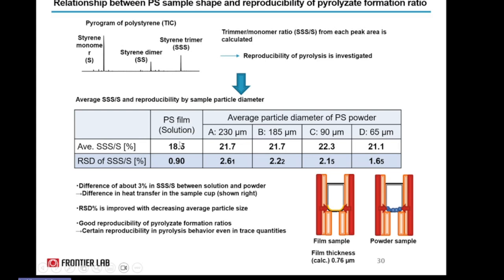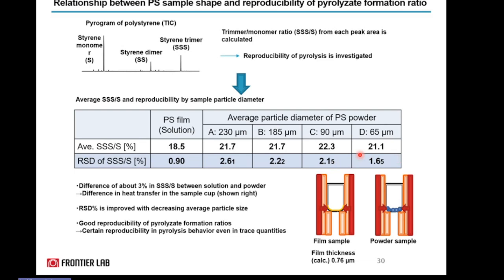As expected, for the solution form we have a better ratio, whereas this is slightly on the higher side for the powder. So it's always recommended, if we can bring it to solution, to do it as a solution, as that is the best thing. But many of these polymers do not have the solubility. So we have to compromise a little on the reproducibility and sensitivity, and then get the best out of it. When we compare the relative standard deviation for different sizes, as the size gets smaller, you can see the RSD is improved. So you have the best reproducibility, or relative standard deviation, for the smallest size.